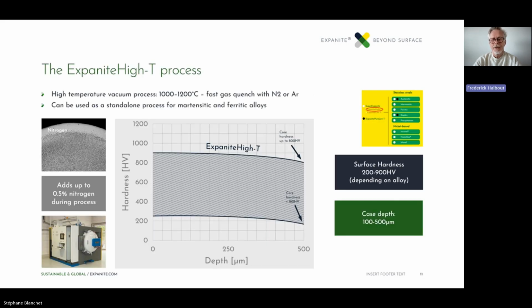The yellow dot here explains what we do as a treatment that we call SuperExpanite, which is a combination treatment. And to give you a little bit of an image of what we are doing for this SuperExpanite treatment, it is in 2 steps. The first step is called Expanite High-T, which is a process conducted in a vacuum chamber at a high temperature up to 1150 degrees Celsius.